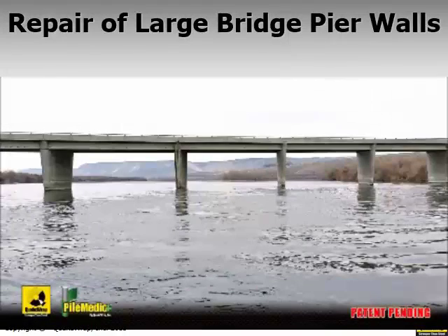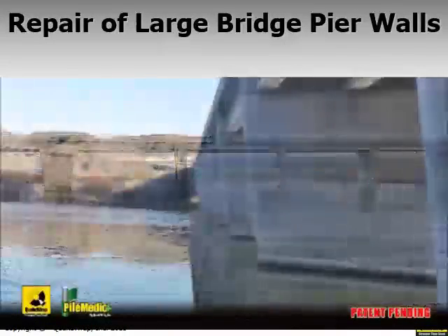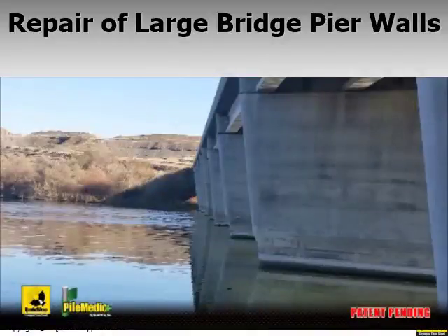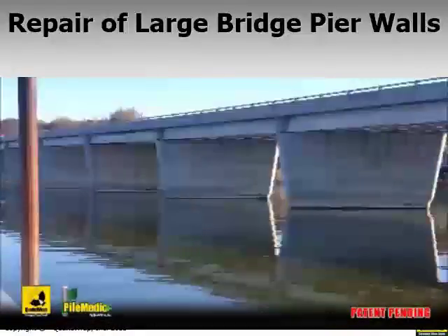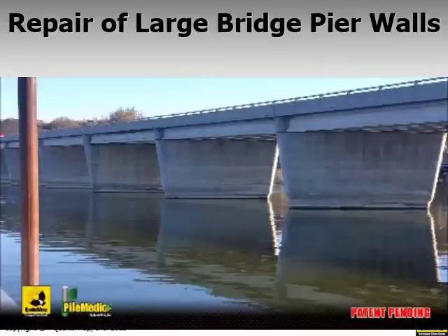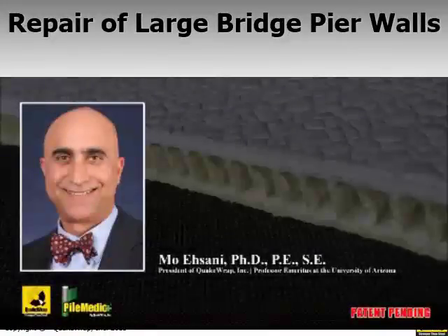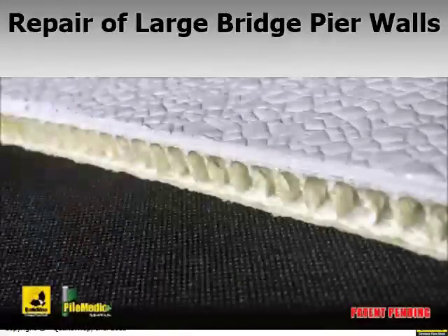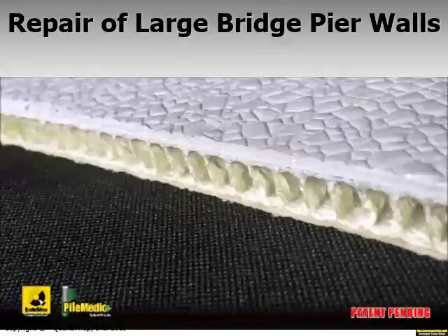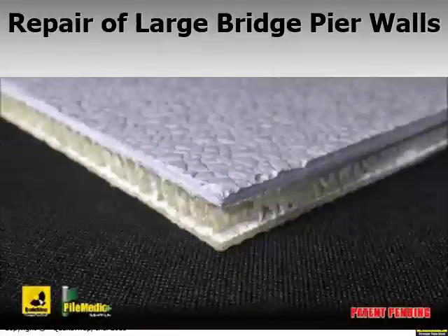For example, the bridge piers shown here often corrode in the splash zone with the tidal or wave action. Typical repair requires adding new reinforcing steel and concrete to that region to make up for the lost capacity. QuakeWrap offers a patented technique developed by Professor Mo Ehsani to quickly strengthen such structures. The technique requires the use of spacer sheets that are wrapped with conventional fiber-reinforced polymer, FRP, wet layup.